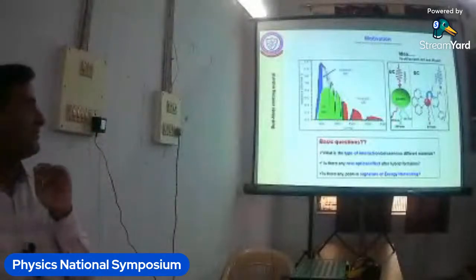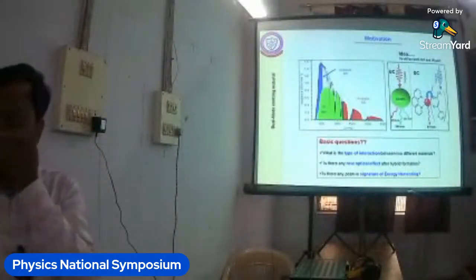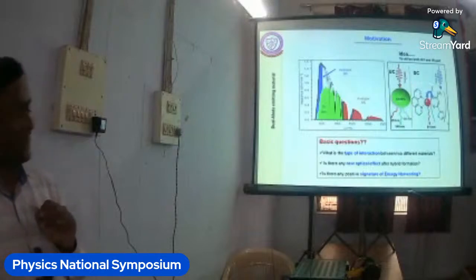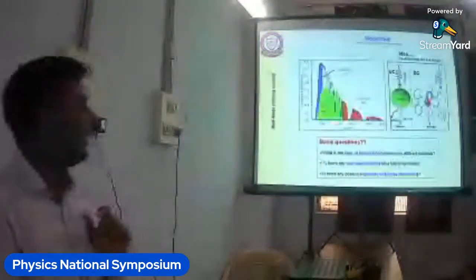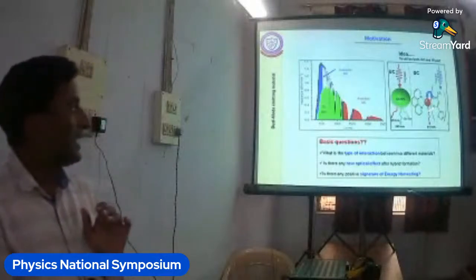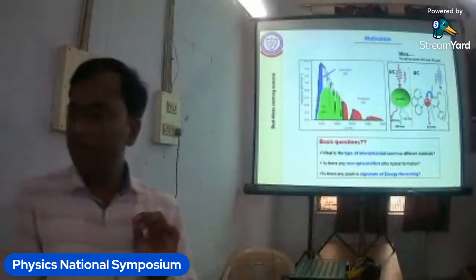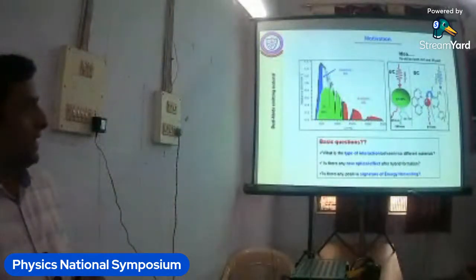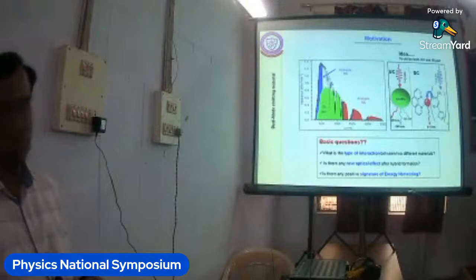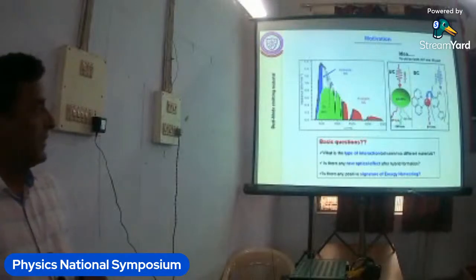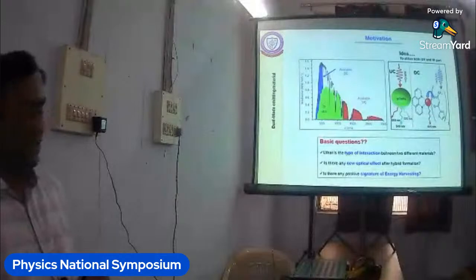You can excite with infrared light, and then it will emit in the green and red region. The second material that we selected, which can be excited by UV light, was an organic complex having europium 3+ as an activator. This can be excited by UV light, and it gives emission at 611 nanometer, meaning the red region. So these two materials give emission in the green and red region.